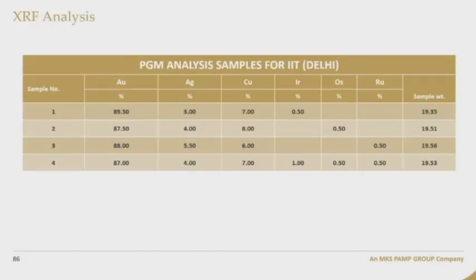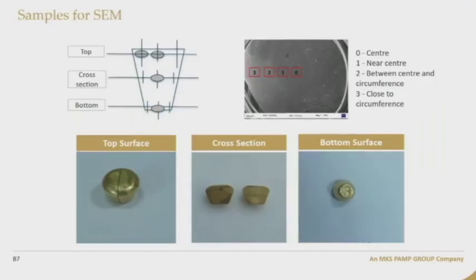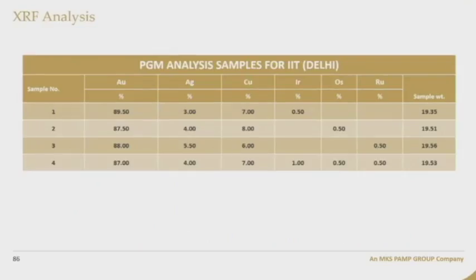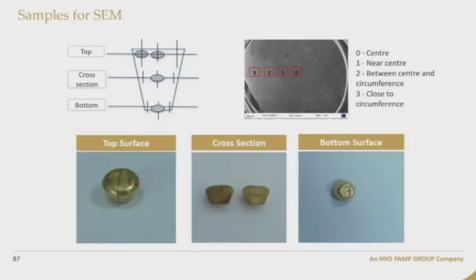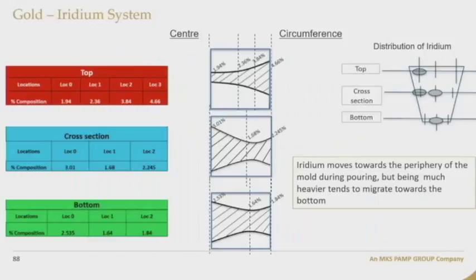Now, as Pankaj had indicated, we made this sample to test through scanning electron microscope. We made 4 samples, one with 0.5% iridium, second with 0.5% osmium, third with 0.5% ruthenium. And we also made a mix of 1%, 0.5%, and 0.5% iridium, ruthenium, and osmium. And we tested it at locations 0 to 3 on the top surface, cross section, and at the bottom. And what do we get?